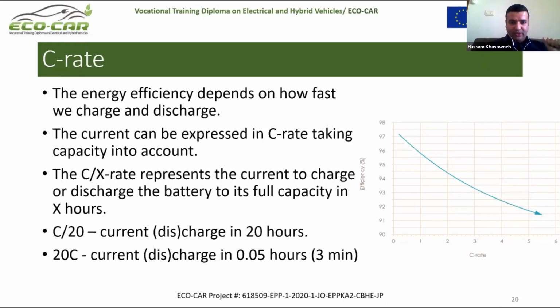So why is that important? Because the efficiency is a factor of C rate. When we say efficiency, here we mean the energy efficiency, not the coulombic efficiency. So when we say that our efficiency is 97%, that's true when your C rate is very, very small. But when your C rate is very large, like 5, 6, 7, 10, then you can expect the efficiency to drop to 90 or maybe 85%. So it's not really true to say the battery efficiency is just 90% if you don't continue the statement. You need to define the C rate. It means how fast you're charging and discharging your battery. So this is a very important factor.